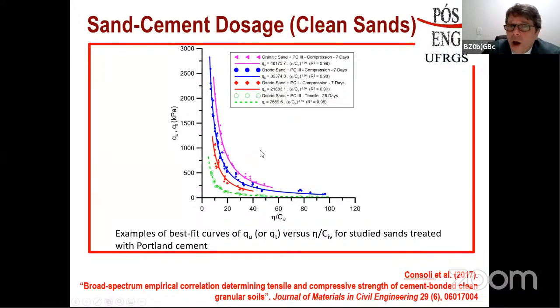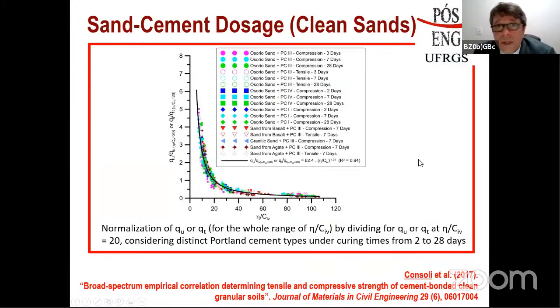When I do that for all the tests, I get a unique curve, which means a unique eta over civ with a power of 1.38 works for all the specimens of granular soils that we tested, with different roughness, different angularities, different amounts of cement, for tensile and compressive strength and different curing times. So the shape of it is unique, which is quite important.